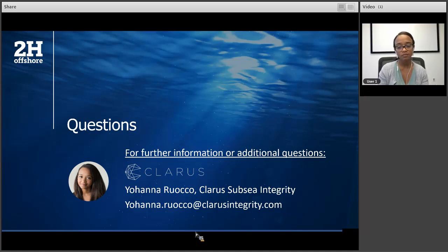Okay, thank you. Next one, what is the approach for defining KPI limits for corrosion rate? We look at both allowances that were considered in design, as well as the service life and what the corrosion models tell us about the CI inhibition efficiency, and that's how we arrive at the limits of acceptable corrosion rate.